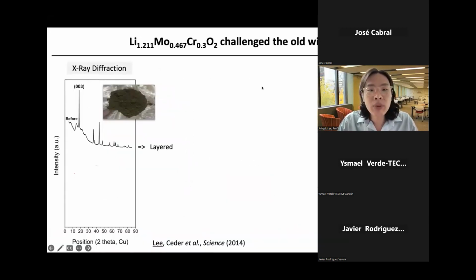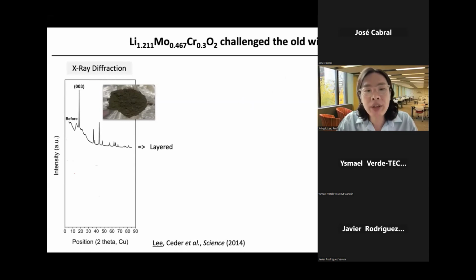But in 2014, my colleague and I developed an interesting new material called lithium molybdenum chromium oxide with this particular composition, which challenges the conventional wisdom that the disordered rocksalt material is a poor cathode material.